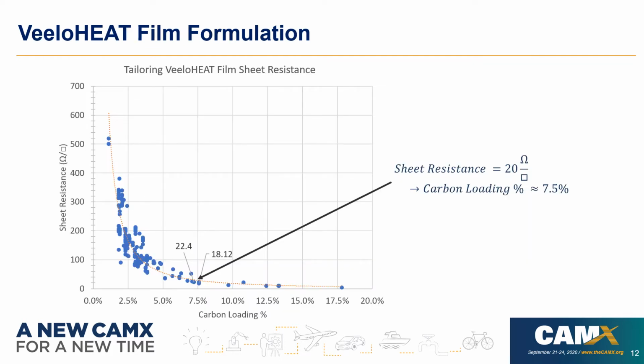So going back to our 12 inch by 12 inch heater blanket design case study, we found that we needed to manufacture a 20 ohm per square electrothermal film. How we would do that is we would tailor the content of the carbon in that film. So in this case, we have a curve built out. We would need roughly 7.5% loading to achieve that 20 ohm per square target. So then once we have that formulation, we would send it off for manufacturing.